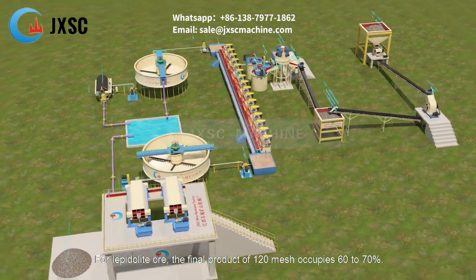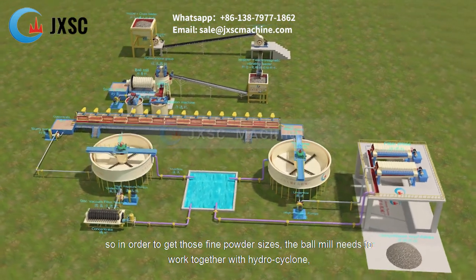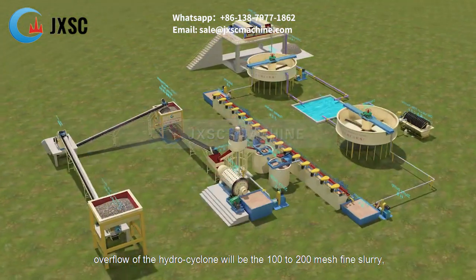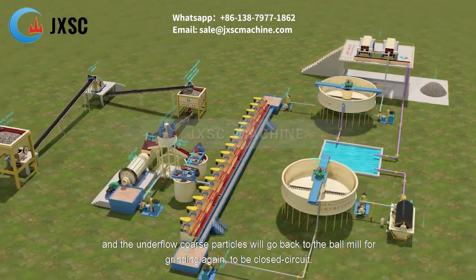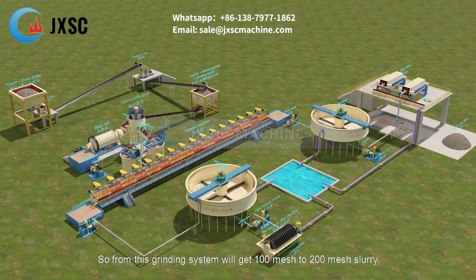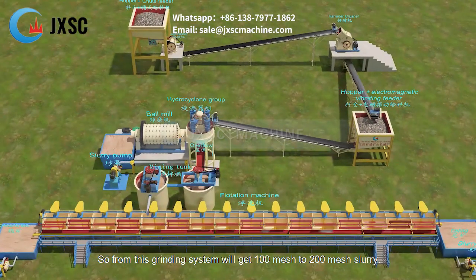For lepidolite ore, the final product of 120 mesh occupies 60 to 70%. So in order to get those fine powder sizes, the ball mill needs to work together with a hydrocyclone. Overflow of the hydrocyclone will be the 100 to 200 mesh fine slurry, and the underflow coarse particles will go back to the ball mill for grinding again, to be a closed circuit. So from this grinding system we'll get 100 mesh to 200 mesh slurry.